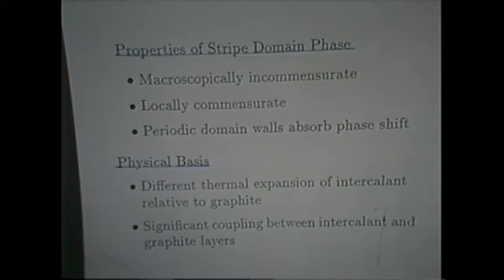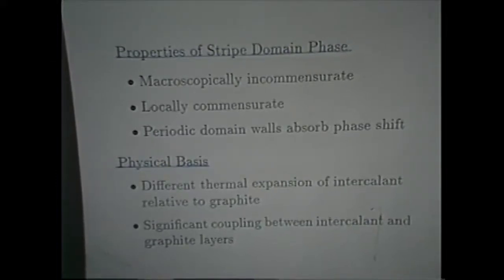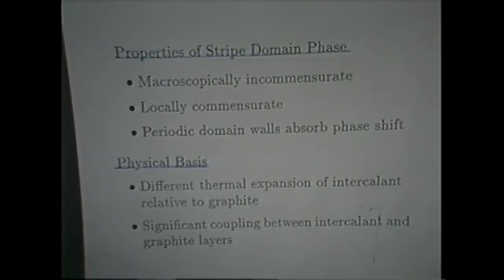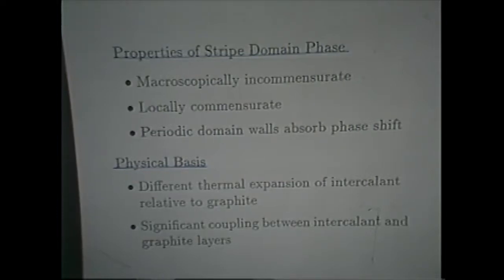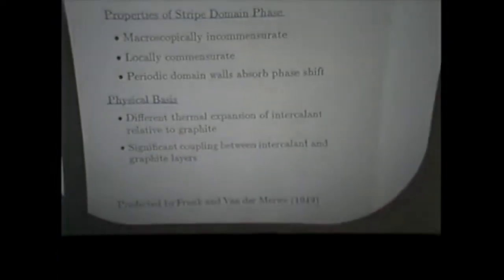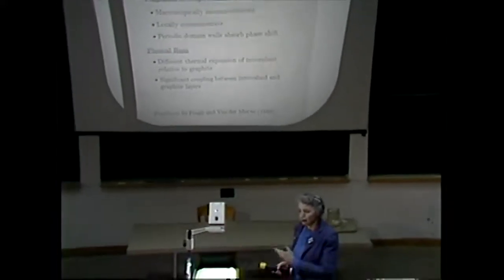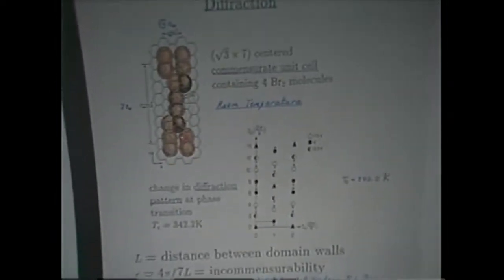The physical basis of why it occurs in graphite is that graphite has essentially no lattice expansion whatsoever, and any intercalant that you put in will have a normal lattice expansion, so it will grow. And as it grows, it wants to accommodate itself to a larger lattice constant. It stays commensurate for a while, but afterwards it decides that this is no fun, and it goes into this stripe domain phase. Now, the evidence for this comes from some very beautiful work that was done in Burgeneau's group. Here's the crystal structure. Here's the bromine molecules registered on graphite. This is the room temperature commensurate phase four bromine molecules per unit cell.